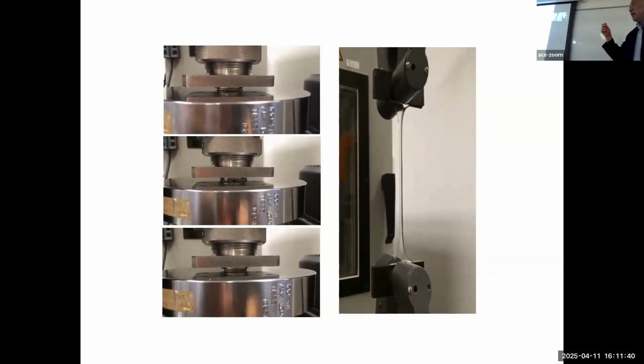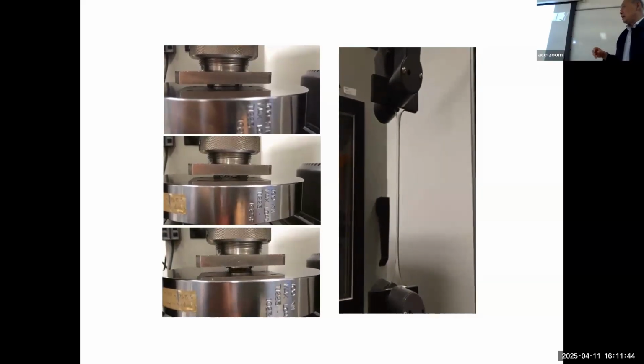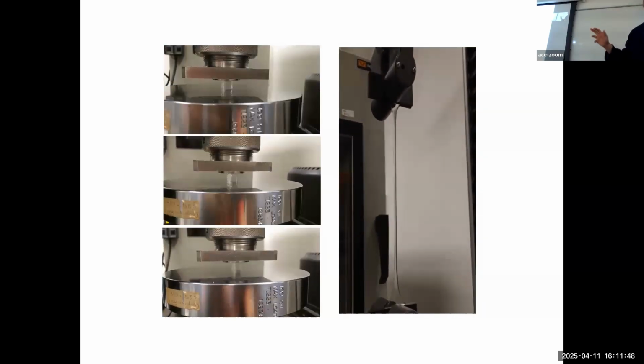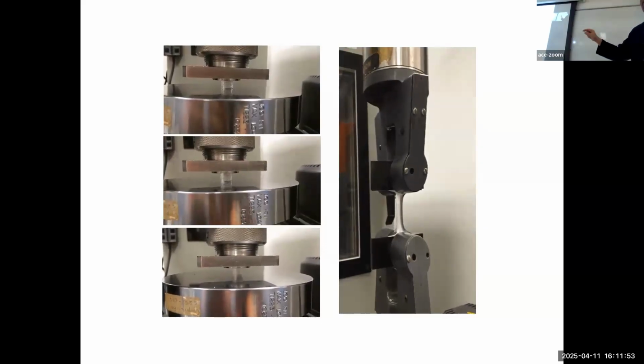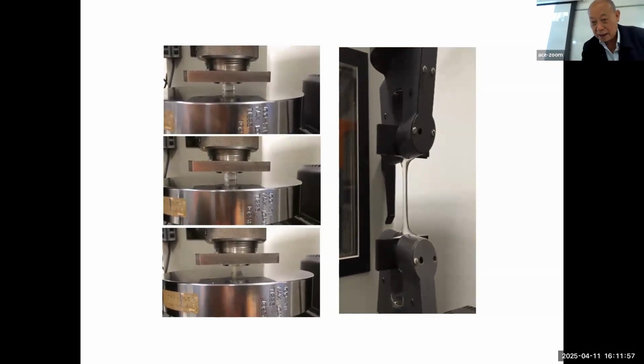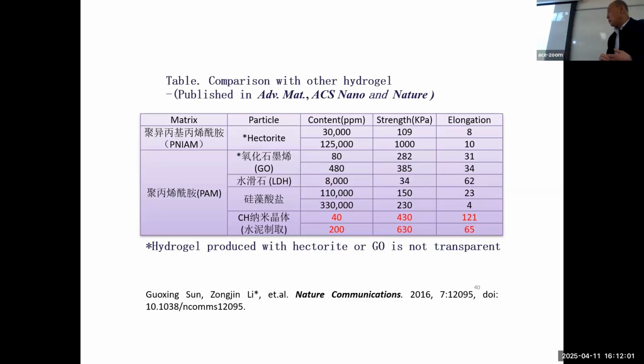And for this tension side, we found the maximum tension can be 100 times over the original size. Okay, so you can see it's without breaking. So this is a very good elasticity. So we have one article published in Nature Communications. We compared with the hydrogel reinforced with other nanoparticles. You can see with our cement produced nanoparticles, the amount we utilize is small, and the strength improvement is almost the highest, and elongation is the highest. So that means we do have good results utilizing cement produced nanoparticle to reinforce the hydrogel.